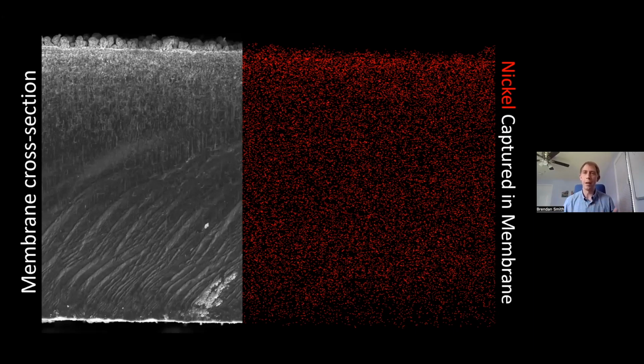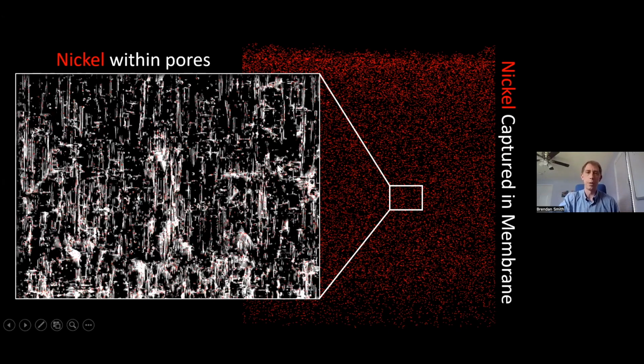So what you can see here on the right side is the actual porosity or the pore structure. We can then zoom in and see a much magnified version of that pore structure. And so you see the individual pores highlighted with the high contrast bright pore structure. And these little nickel seeds signified in red, it's actually the metallic nickel clinging to the side of the membrane. And then as a second step, we can very simply release that back into a very pure stream to then become a solid product like nickel sulfate. So this is just one example. We can do this for all sorts of materials in lithium-ion battery recycling, as well as more broadly in the mining space as well.